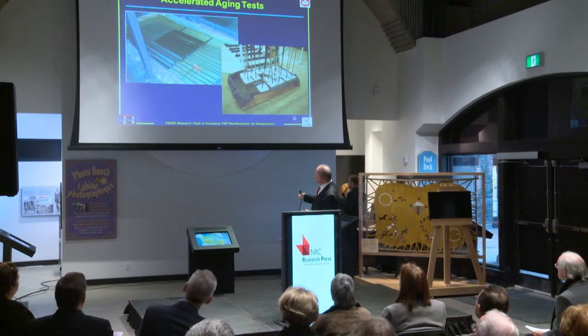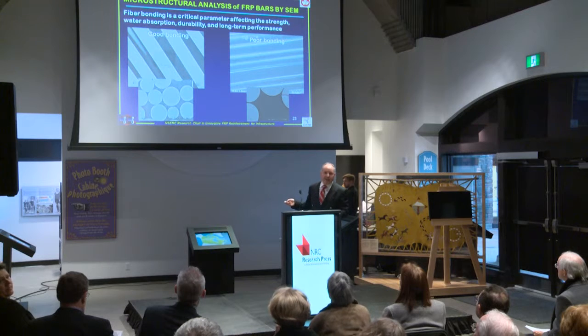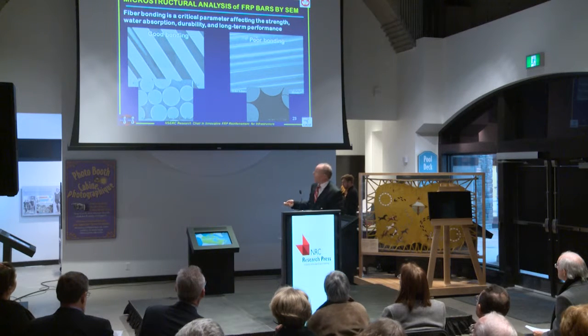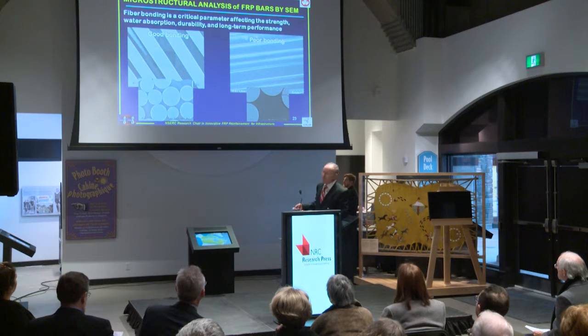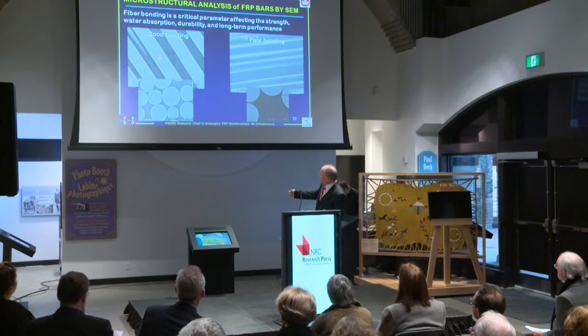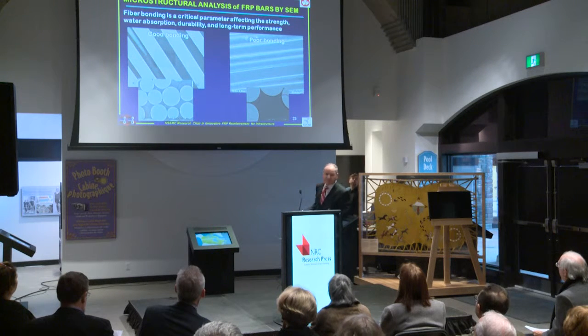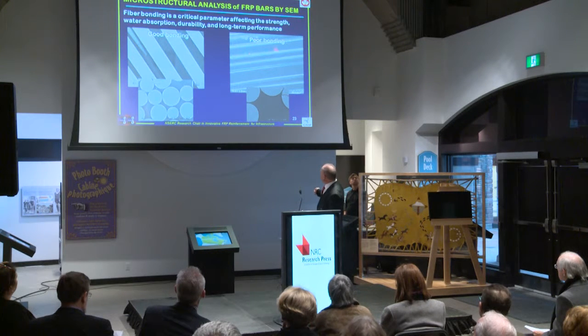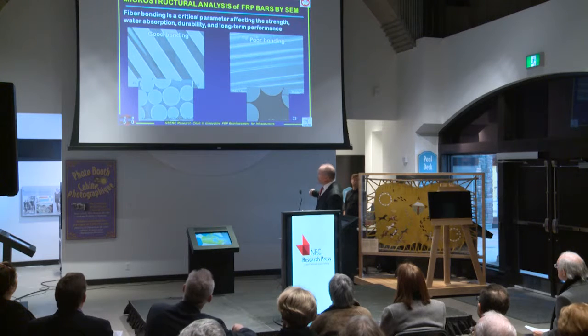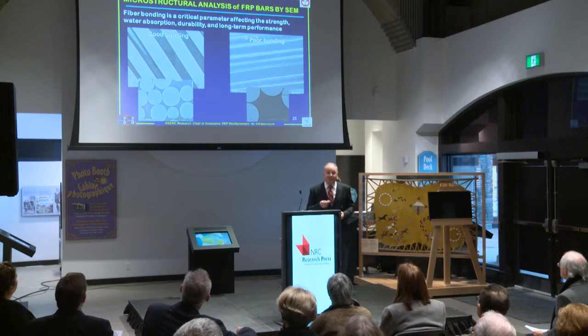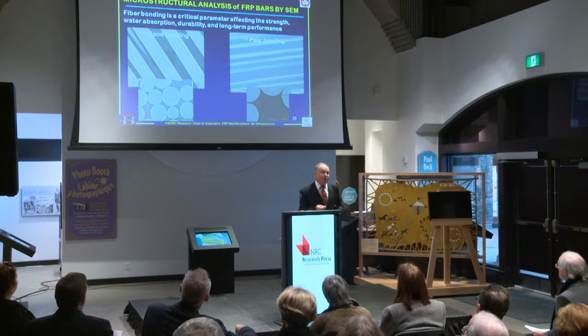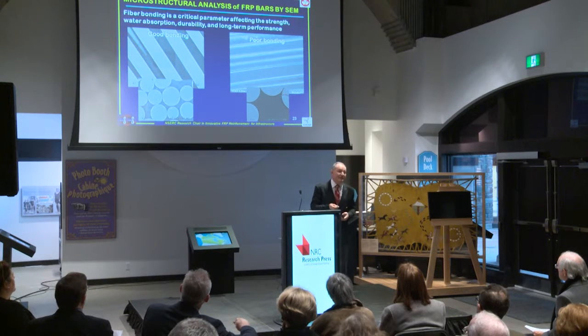Also, as you can see here, some bars. We investigated the behavior of this material, as you know, from SEM analysis, and even through testing we observed this material having very good behavior, a very good bond. This is one fiber, and this is the resin, and here is the interface, and you can see there is no degradation. With some other fiber and other resin that we tested, as you can see here, this is poor bonding, and we can see some delamination between the fibers and the resin. So we have to avoid such behavior, of course, and this material cannot be implemented in the field.